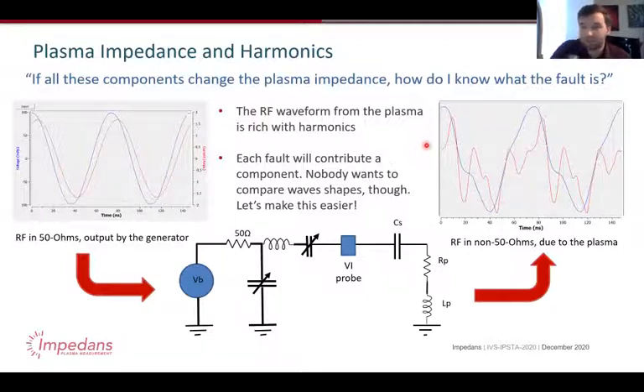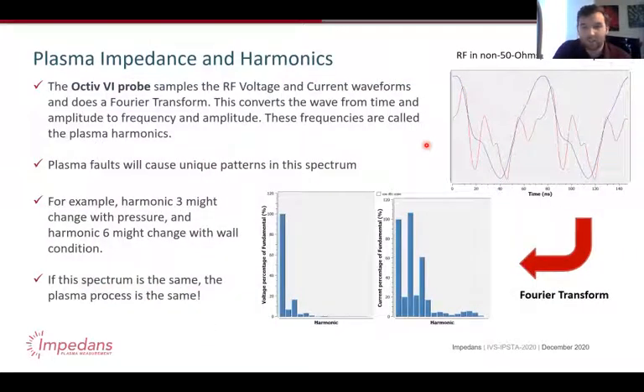Now, no one wants to compare one waveform to another. We can do something more practical. Take a Fourier transform of these waveforms and you get a harmonic spectrum. Like an optical spectrum with different wavelengths of light, here you have a spectrum with different wavelengths of radio frequency. A very typical plasma frequency is 13.56 megahertz. That's the first column here. And then the plasma itself will produce 27.12, 40.68, and all these other harmonics. And as you can see, the spectrum can be quite rich in a real production process.